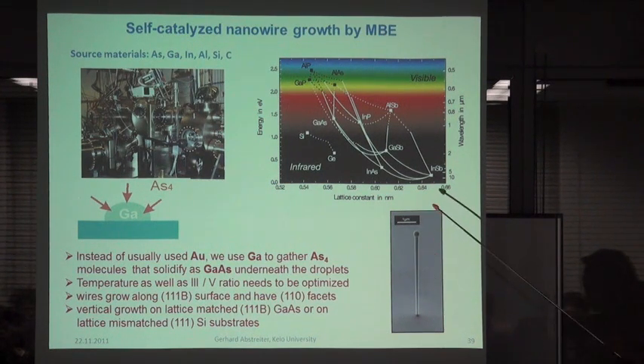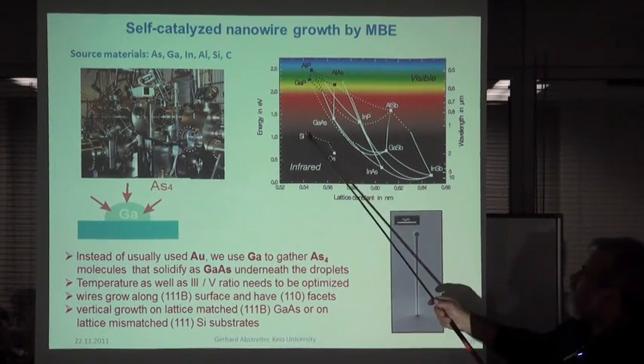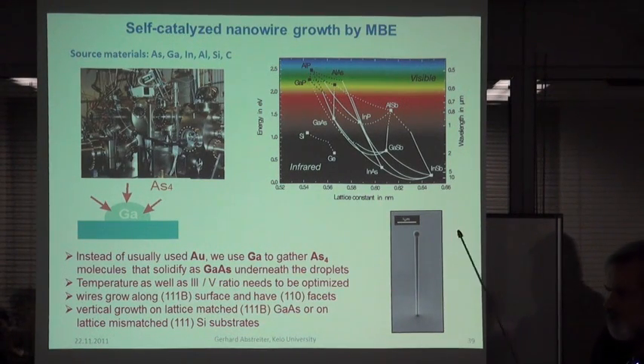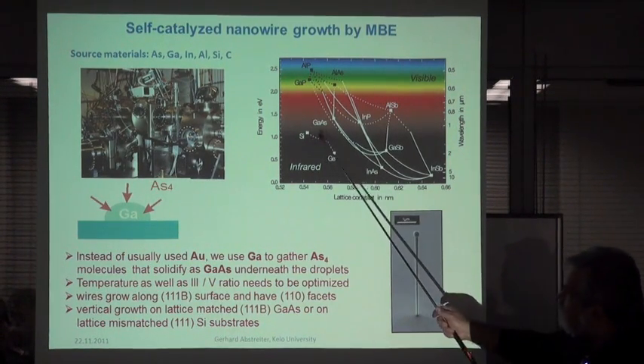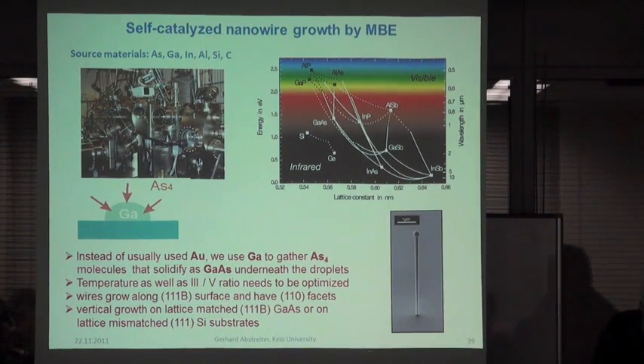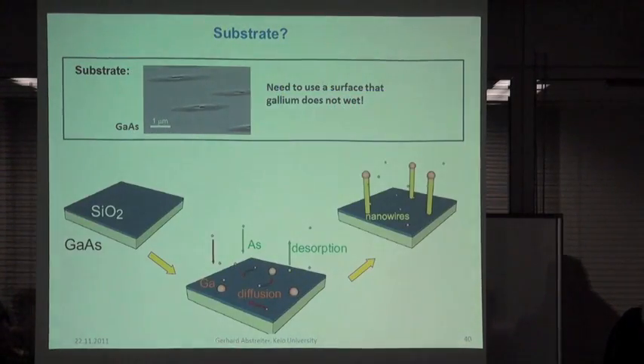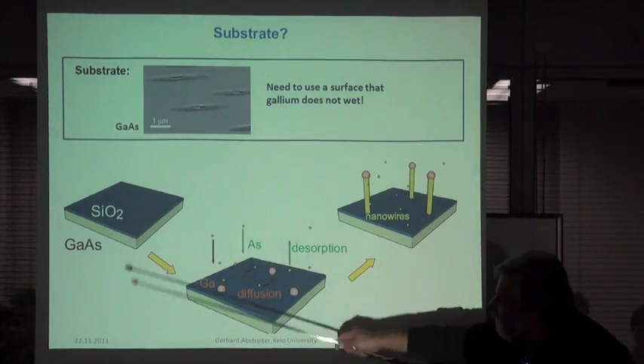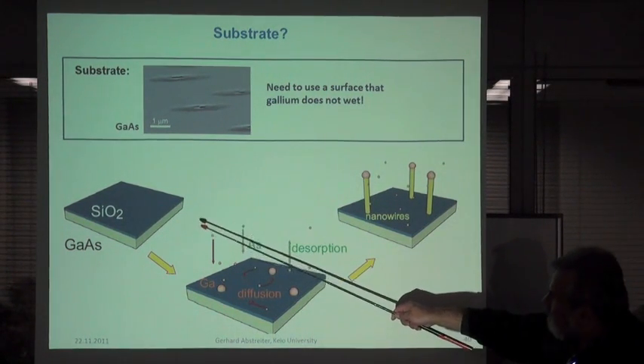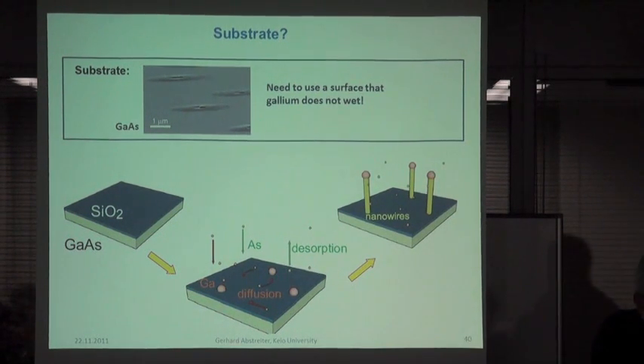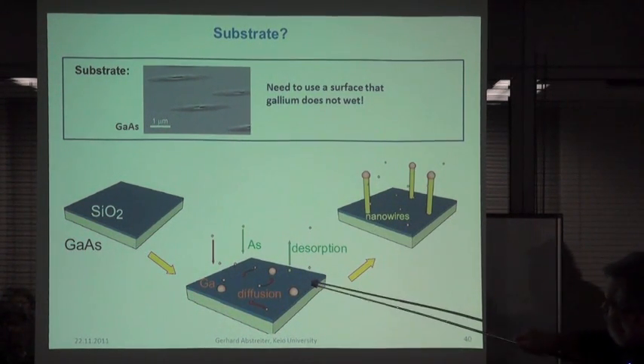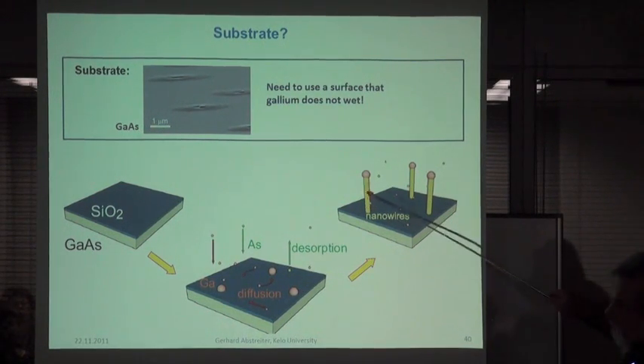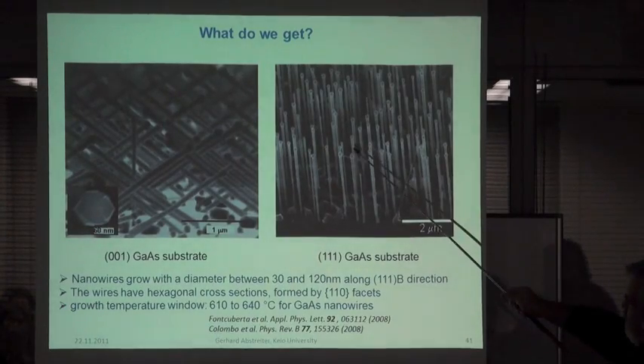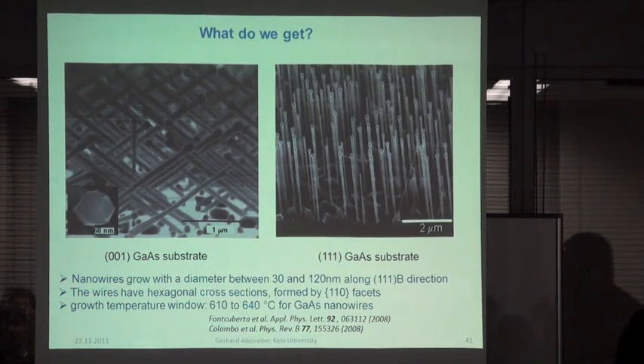And what we can do now is, because this has a very small footprint, we can, instead of gallium arsenide, also use now silicon as a substrate. So it works on silicon, and we can also grow indium arsenide on silicon, even with this large difference in the lattice constant. Let's say on gallium arsenide, we need a thin silicon dioxide, because otherwise gallium is more wetting the surface but not making droplets. And this is so thin that we then have pinholes where we nucleate the gallium and then we get the wires.